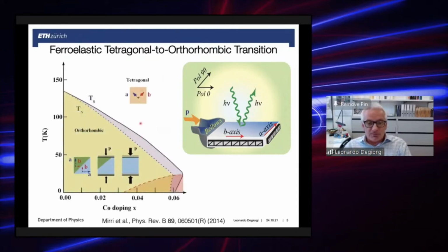Obviously, temperature, because of the various phase transitions, today because of the phase transition into the superconducting state, but also as a function of uniaxial stress, which turns out to be an important tunable variable. It allows you, first of all, to circumvent the twinning of the specimen, particularly in the orthorhombic phase, because of the ferroelastic transition. So by applying uniaxial stress, you can actually detwin the materials and induce a single domain, fully detwinned phase, which allows you to appreciate any anticipated anisotropy in any physical measure.